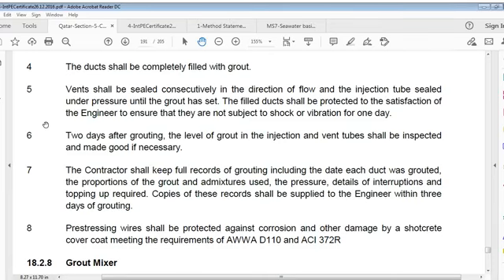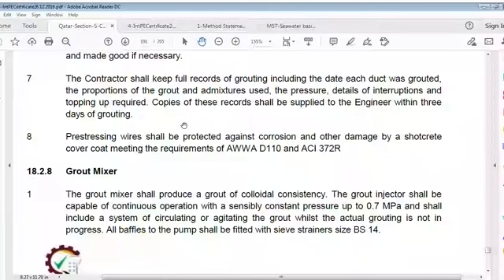Contractor shall keep full records of grouting, including date each duct was grouted, proportions of grout and admixtures used, pressure, details of interruptions and topping up required. Copies of these records shall be supplied to engineer within 3 days of grouting. Pre-stressing wires shall be protected against corrosion and other damage by shotcrete cover coat meeting requirements of AWWA D110 and ACI 372.